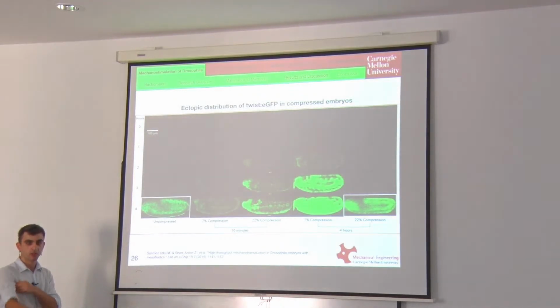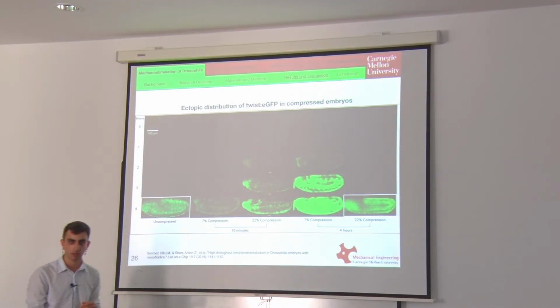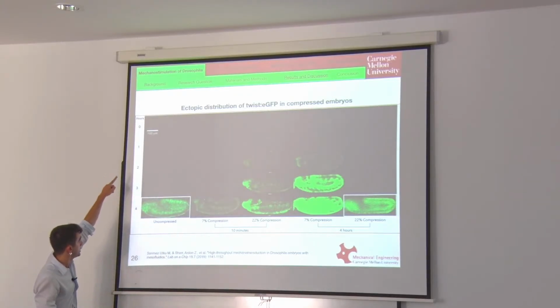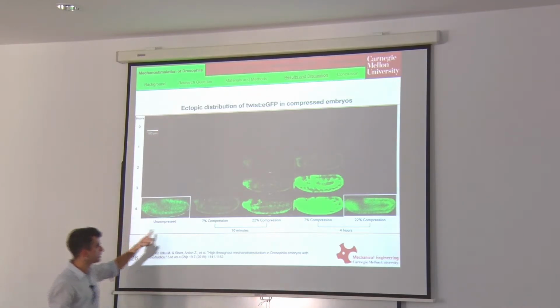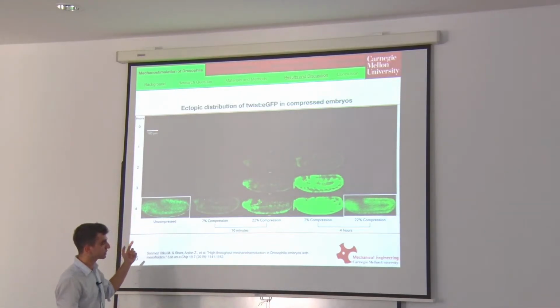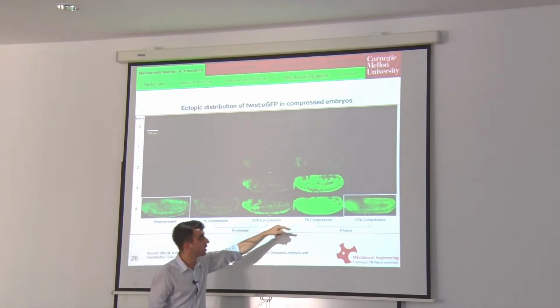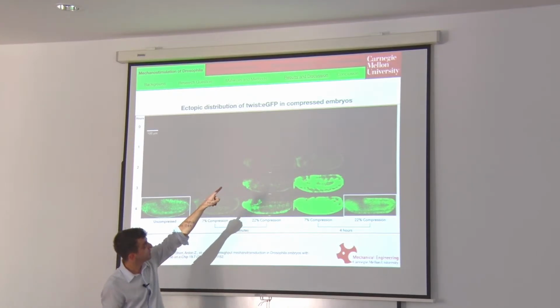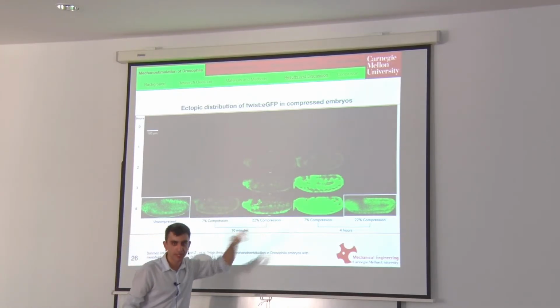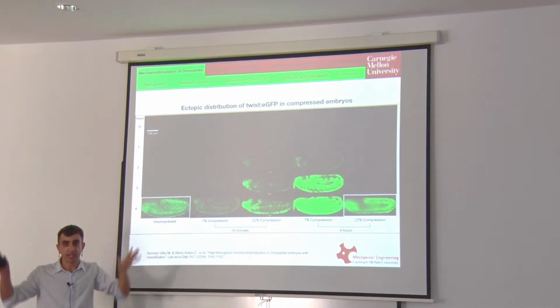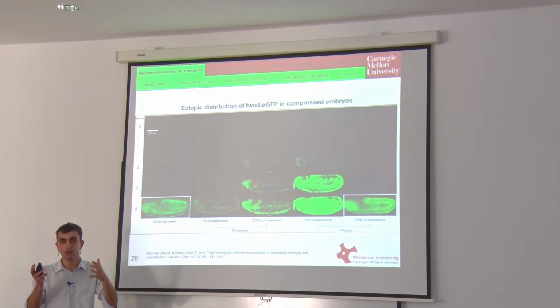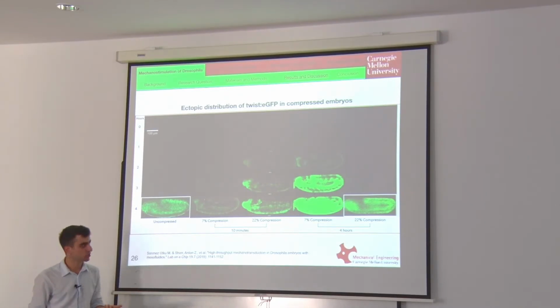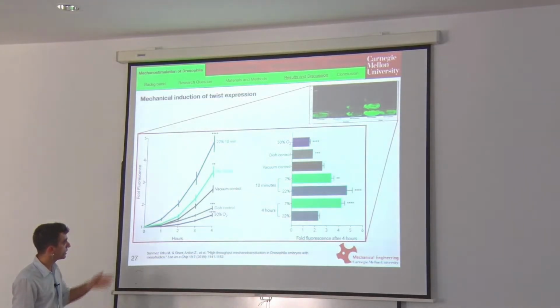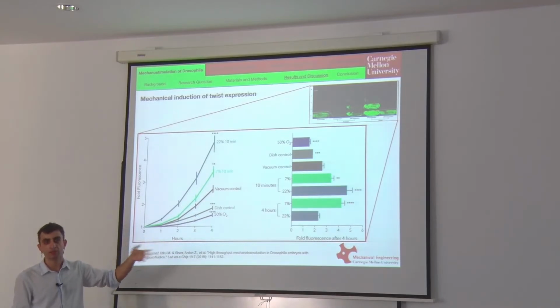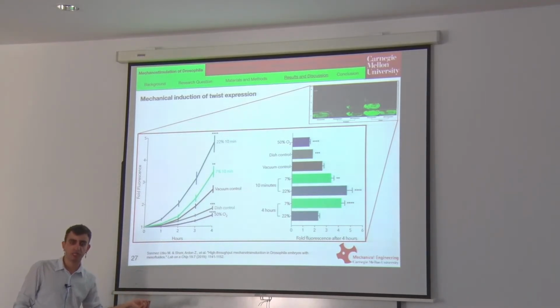So these are the results that we got. We want to measure the twist expression as a result of the mechanical compression. And as you can see, these are the hours passed after compression, and these are the amounts of compression that we apply. And it looks like if we apply mild compression for a long time, we can really induce the expression of twist, which is almost none at the beginning, and it is extremely expressed in an ectopic fashion, meaning homogeneously everywhere because we apply bulk compression, unlike the local compression that is happening during gastrulation. And if you look at it quantitatively, we can also see that there is a dose and time-dependent mechanical response coming from this twist expression in this device.